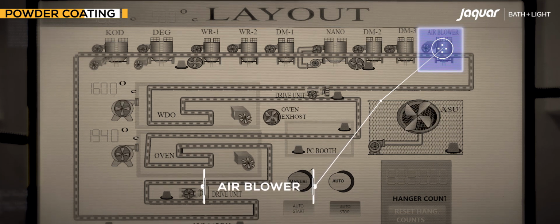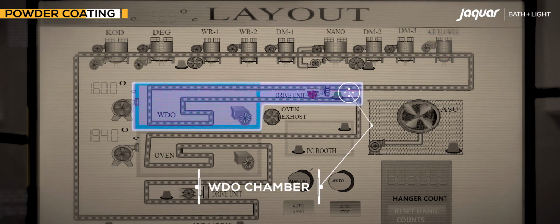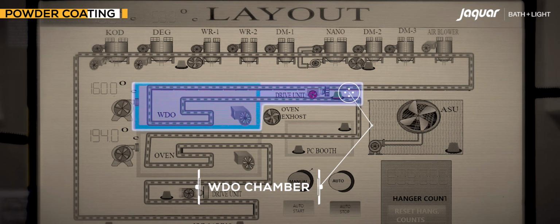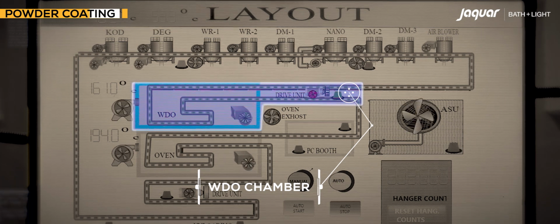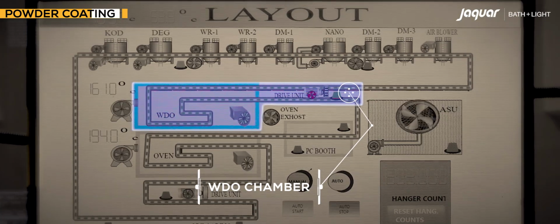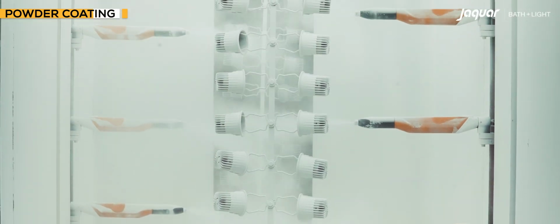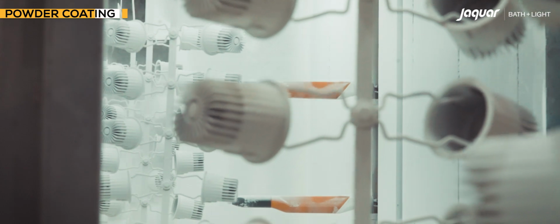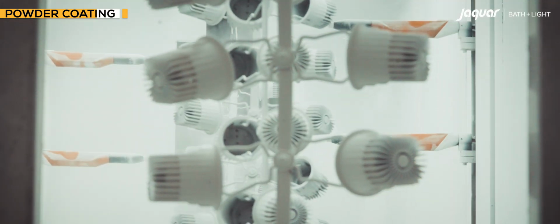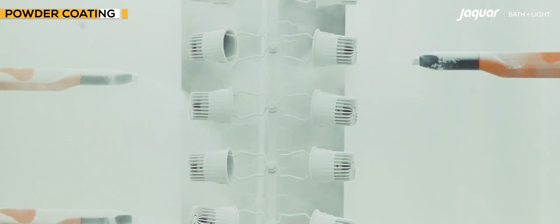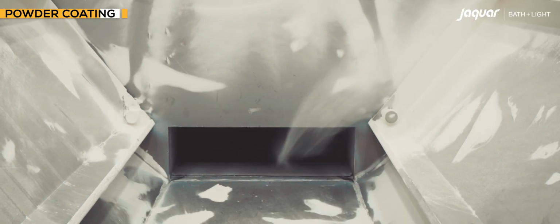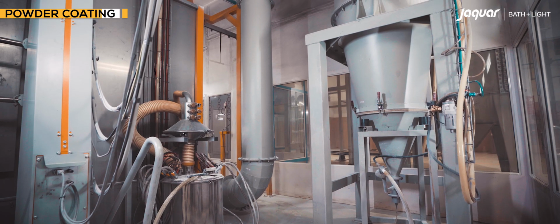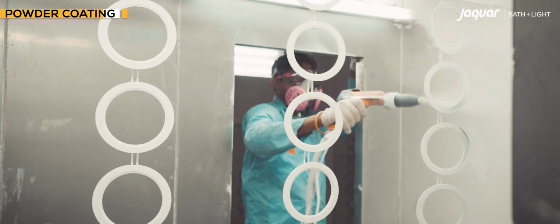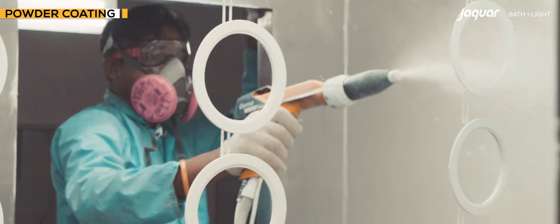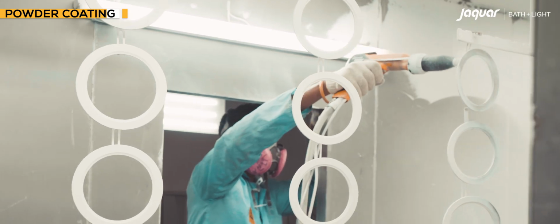Then it passes through the WDO chamber where the temperature is 100 to 120 degrees Celsius to dry water on the surface. The belt goes to a powder coating chamber where 3 automatic guns on both sides spray dry powder continuously on the housing. The powder that falls on the ground is supplied to the cyclone through suction. For any area where powder is not properly coated, powder is sprayed through a manual gun.